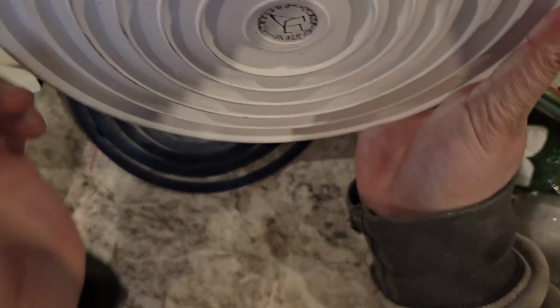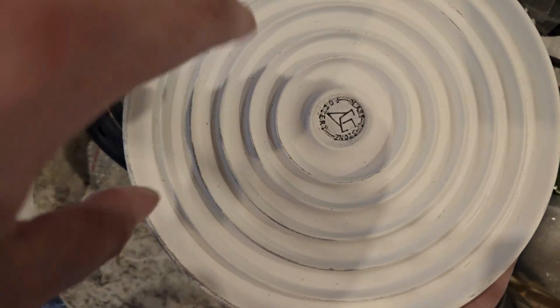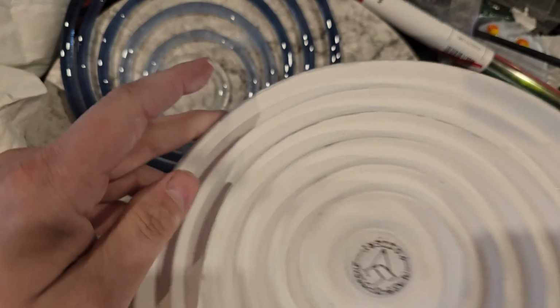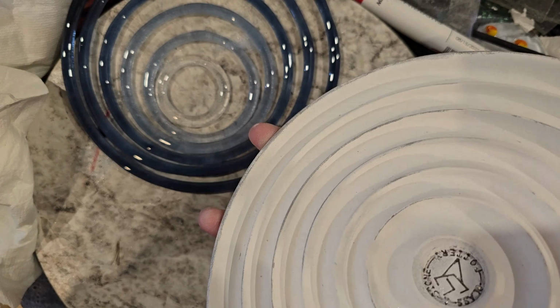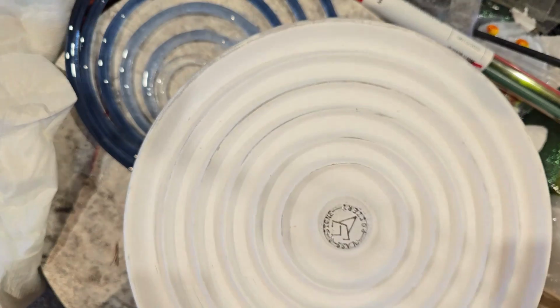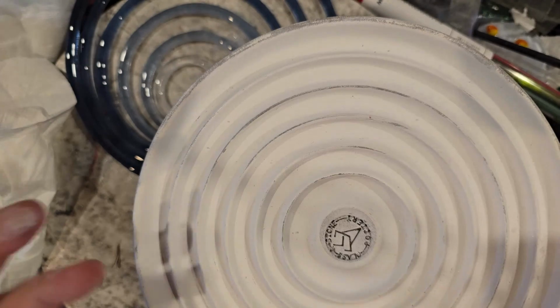is when you spray it, don't just spray it face on, tilt it a little. Because spraying straight down, you're going to miss these edges. So spray at an angle too when you turn and you tilt, because otherwise you're going to get lots of little lines where you have the channel coated, but up the edge is still brown. And remember, these are brown molds, so they should be white when you're done. And if it's still got brown bits that you can see, it's going to stick.